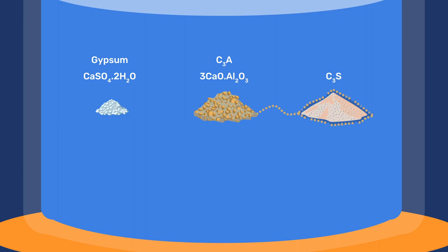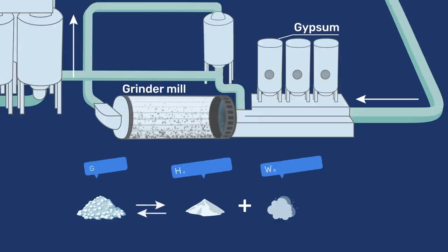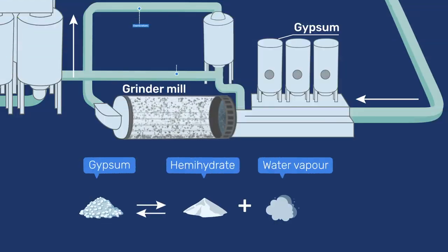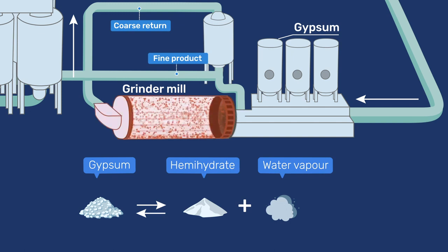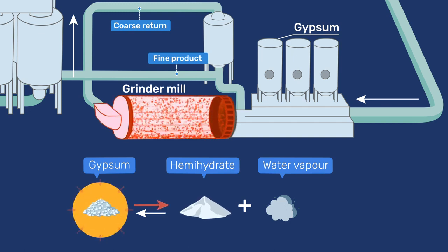If too little gypsum is added, not only will C3S hydration be delayed, but the material will also more rapidly lose its workability. This is referred to as flash set, and probably also explains the short open time of natural cements. Another problem can occur if, during the co-grinding of clinker and gypsum, the temperature becomes too high so as to cause an extensive decomposition of gypsum to hemihydrate.